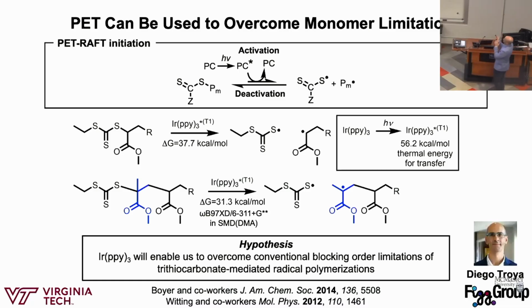And so what we did is we did some calculations. This is the amount of energy that iridium ppy has once it gets excited. It's known that iridium ppy undergoes energy transfer with these sorts of RAFT agents. So we're looking at the amount of energy for energy transfer. That's 56.2 kcal per mole. If we look at our methyl acrylate chain end bond dissociation energy versus our methyl methacrylate chain end bond dissociation energy, obviously this bond dissociation energy is lower because we're forming a tertiary radical. So it's a more stable radical, and the bond dissociation energy is lower.